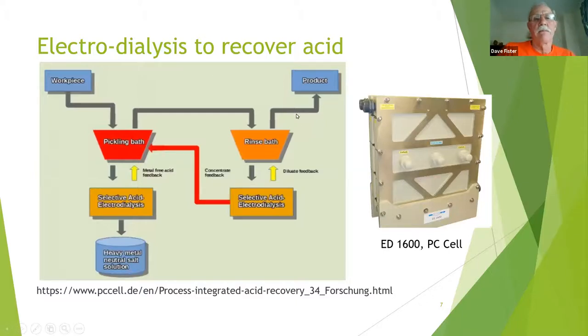Okay, electrodialysis. This is a fairly new technology, and I only found one company, this PC Cell from Germany. The way their schematic is set up here, they've got a pickling bath that has this acid electrodialysis, and then their pickling bath rinse tank also has a system set up. Same technology. So what you have going on is you are removing the heavy metals from the pickling bath, and then you're sending metal-free acid back to the pickling tank. In the case of the rinse tank, now you've got basically water going back into the rinse tank, and then the concentrated acid being pulled out of the rinse tank now going back to the pickling bath.